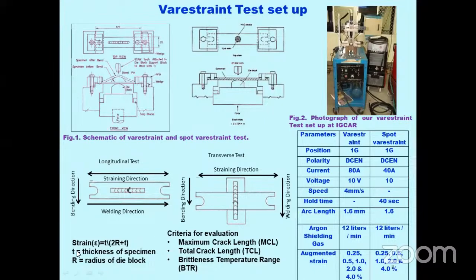The strain augmented on the specimen is calculated by the formula T by 2R plus T, where T is the thickness of the specimen and R is the radius of the die block. By changing the die block radius, we change the strain imposed on the specimen. From this experiment, we get the maximum crack length, total crack length, and brittle temperature range. These parameters are used for evaluation of the cracking susceptibility.